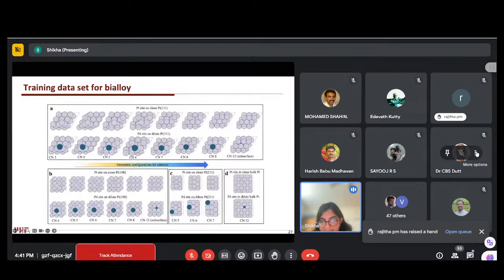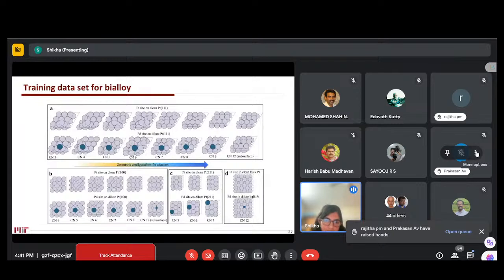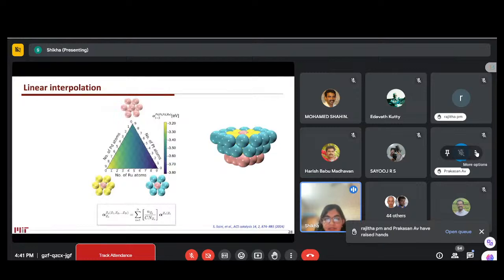How did we arrive at these 18 surfaces? We did a lot of testing and training by including all the possible configurations on the 3x3 surfaces. From there, we determined that we need 18 DFT binding energy calculations for a given surface, and that gives the best alpha parameter. Then we can predict the binding energy by changing the composition. Suppose I have 3 or 4 metal atoms, then I need all the given pairs like platinum, copper, palladium. That way we calculate the alpha parameters for the given pairs.